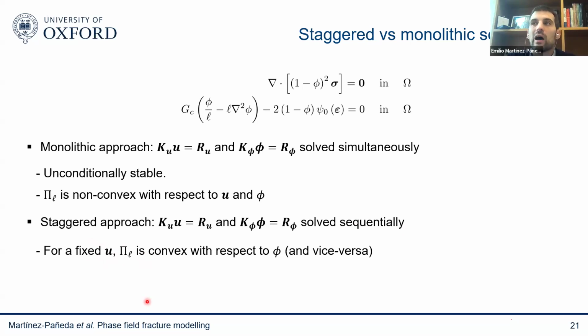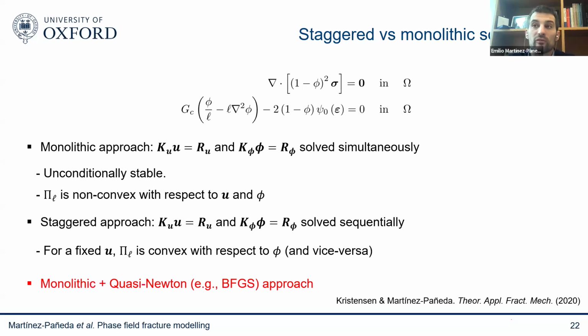So convergence is very, very good. It's very, very powerful. However, when you're using a single pass approach, for example, you're going to lose that unconditional stability. So it becomes sort of like a semi-implicit method. You really need to use small increments. So the approach that we have championed, and also others, in particular Wu's group here in China, is to use a monolithic and quasi-Newton approach. For example, methods like the BFGS, because that gives you the robustness of the staggered approach with the ability of having an unconditionally stable method as the monolithic approaches do. So it's the best of both worlds, basically. So I'll show you in a minute how it works.